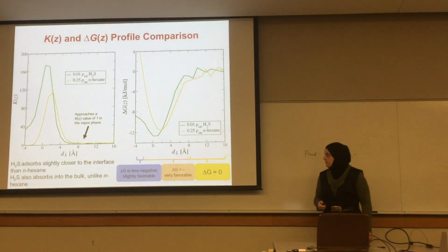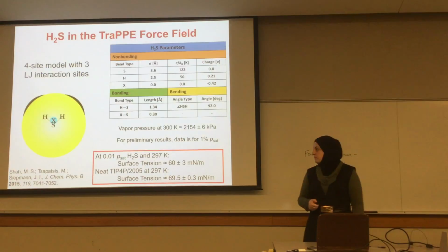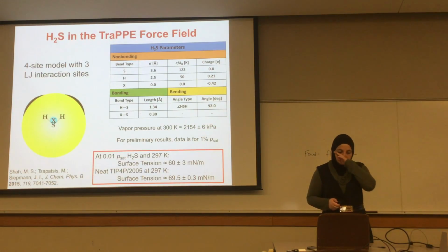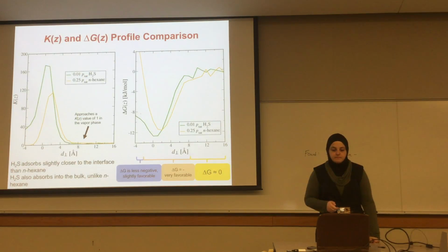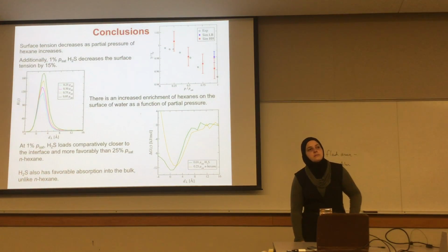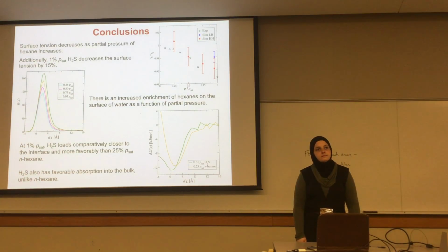I can answer no, because we have looked at hexane on gold surfaces and graphene, and the critical temperature is way suppressed because you have interactions only in one direction. So 300 Kelvin is way above the critical point. So no islands. It's very far above the two-dimensional critical temperature of hexane.